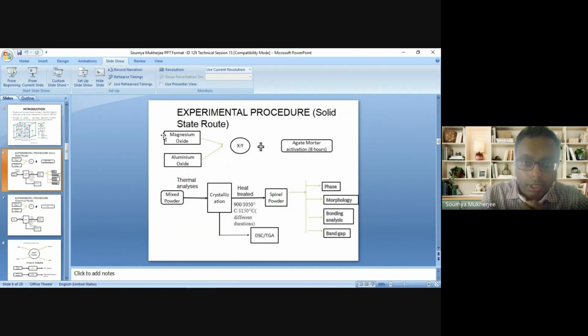Now, this is one of the experimental process routes, the modified solid state process, that I have carried out. For this process, we have taken AR grade materials, magnesium oxide and aluminum oxide, in molar ratio. We have to activate them by means of agate mortar activation for several hours. In our case, it is 8 hours.